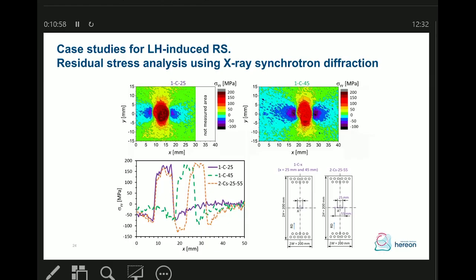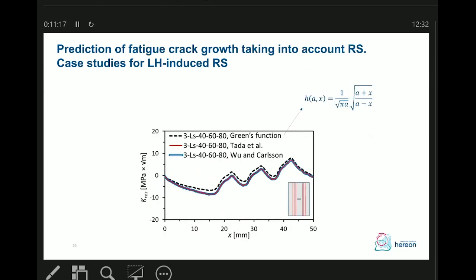And as you can see, for some cases we also have a gradient in the y direction with regard to residual stresses, in principle in the case where we have circles. In the case of lines, we have more homogeneous residual stress profiles. Next slide. And here are the results of the calculation of the residual stress intensity factor due to the presence of residual stresses. Here you see we already have very good results applying the simplest weight function.